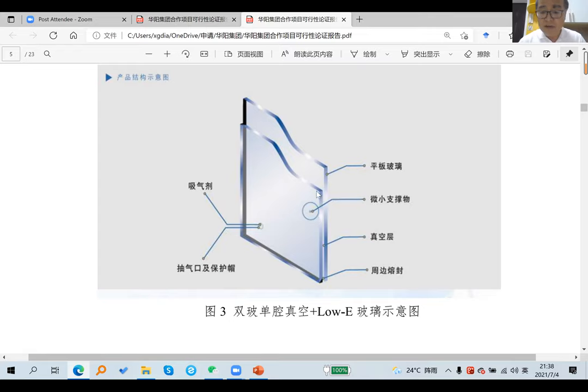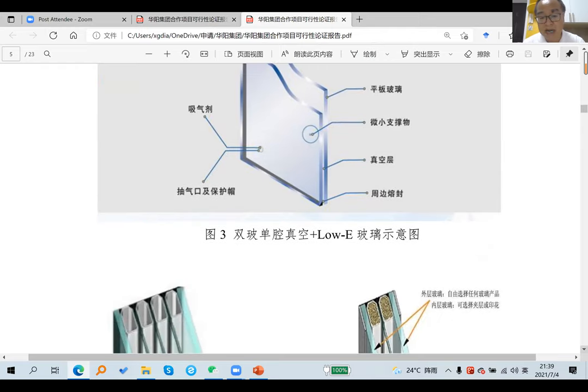Therefore, for such vacuum glasses, the U value, or thermal conductivity, is less than 1.0 watt per square meter per Kelvin. Sometimes the minimum can be 0.5 or so. It's very energy efficient. But the problem is that it is very difficult to process and fabricate, because it must be made in vacuum factories, not like glass that you can cut as you like. If you cut it, it is completely broken.